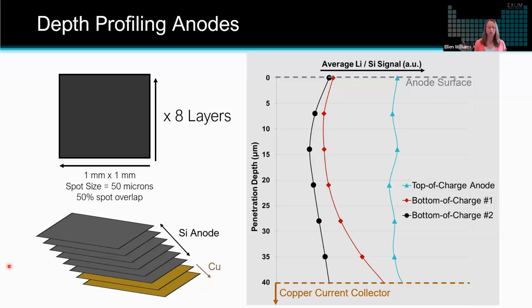And we can see that overall, there's more lithium at the top of charge. That's what we would expect. Those lithium ions should be in the anode at the top of charge. And what we also see is there's a fairly consistent amount of lithium in those different layers. And so that is validating that, it seems that we have the right size of our electrode. We're getting a nice uniform distribution of our lithium ions at the top of charge.